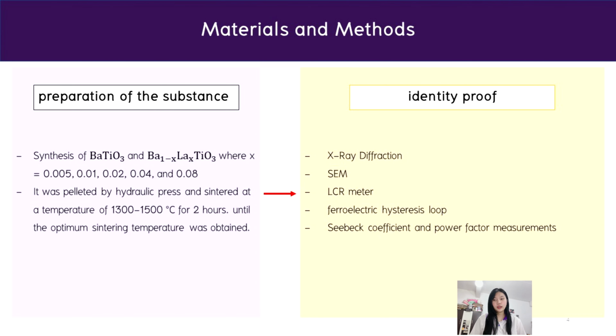Next, preparation of the substance. Synthesis of barium titanate and barium titanate doped with lanthanum, where x is the lanthanum concentration. It was pelletized by hydraulic press and sintered at a temperature of 1300 to 1500 Celsius for 2 hours, and analyzed by X-ray diffraction, SEM, LCR meter, ferroelectric hysteresis loop, Seebeck coefficient and power factor measurement.